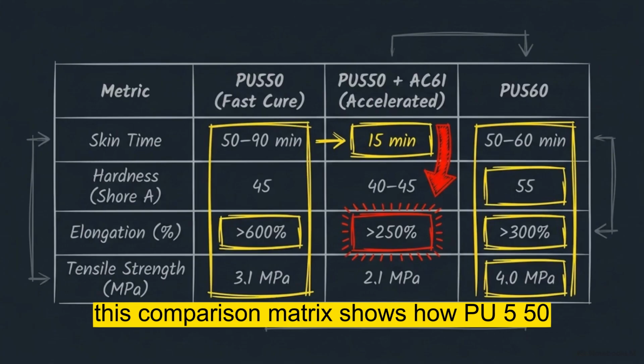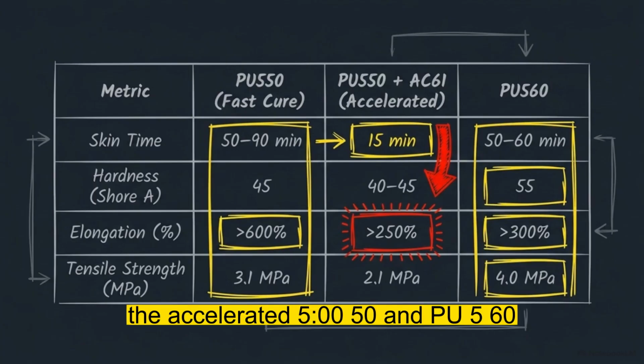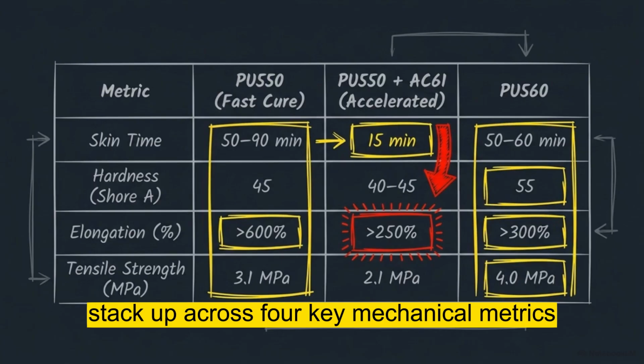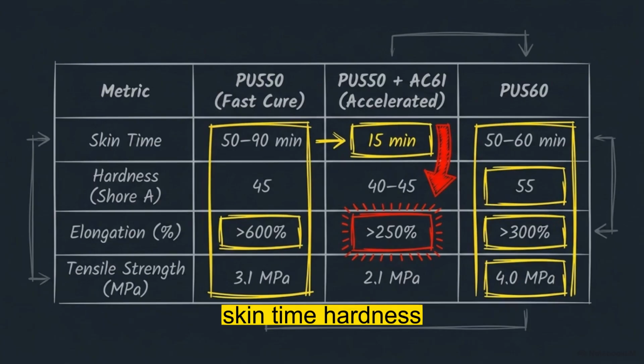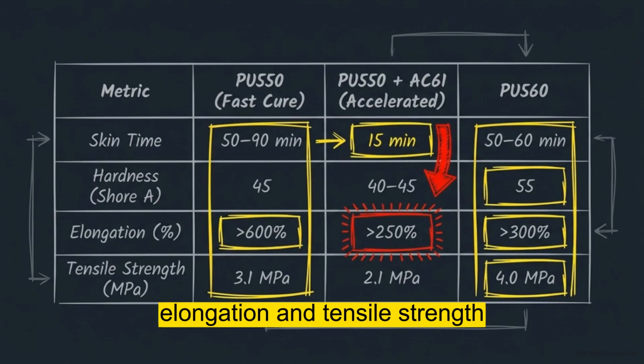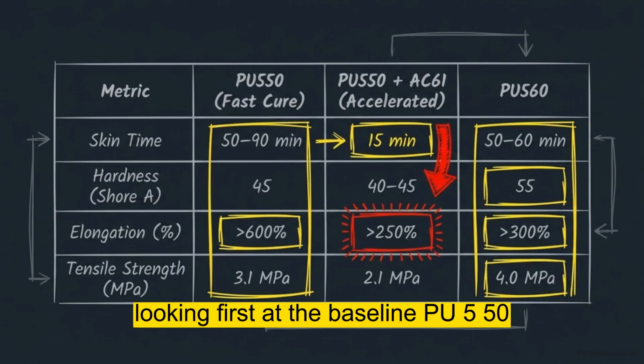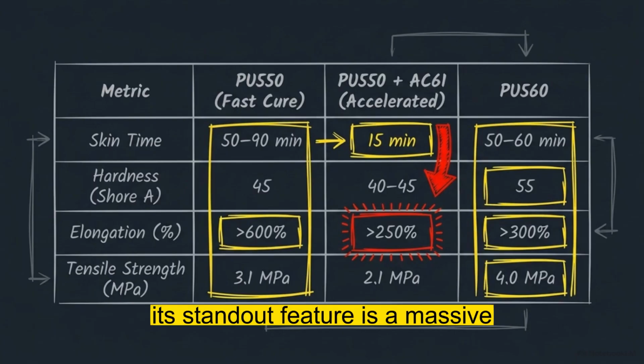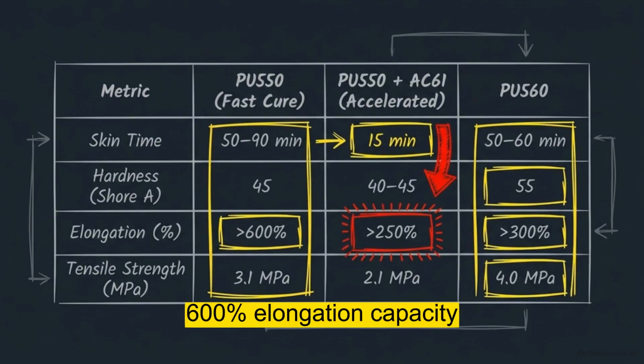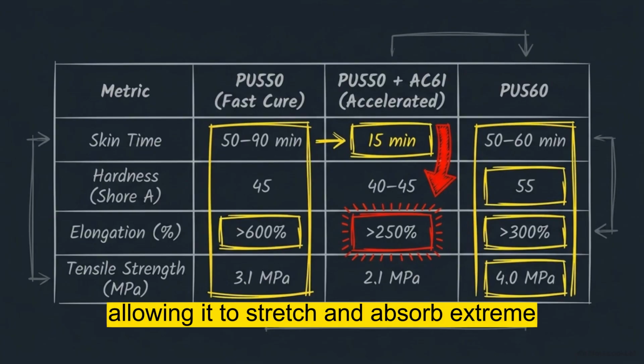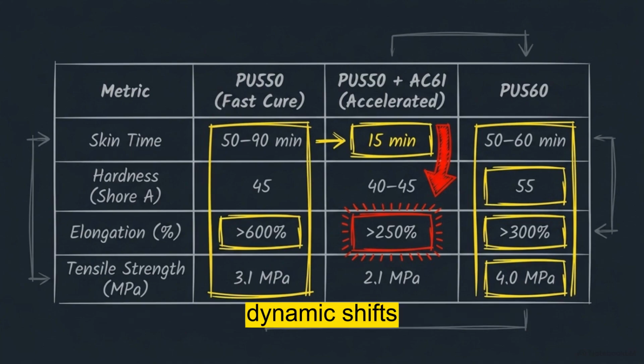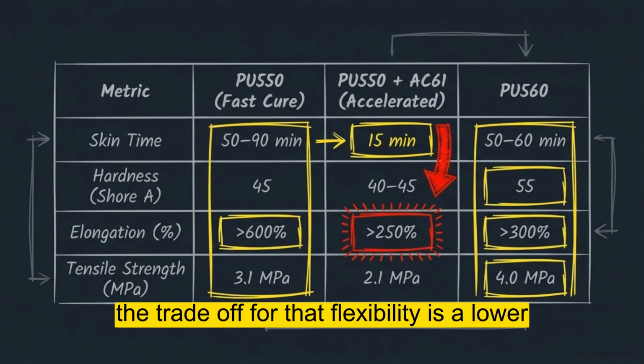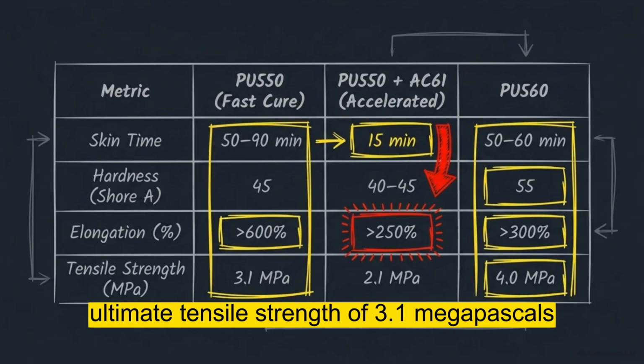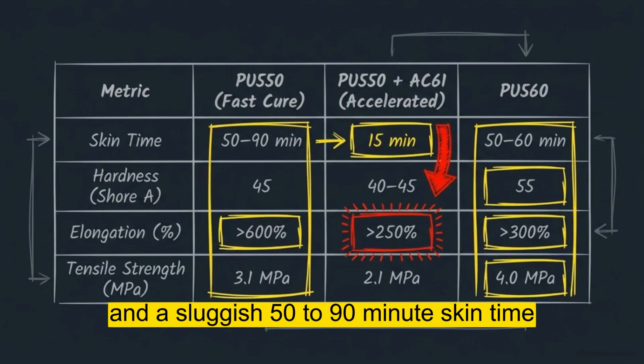This comparison matrix shows how PU550, the accelerated 550, and PU560 stack up across 4 key mechanical metrics: skin time, hardness, elongation, and tensile strength. Looking first at the baseline PU550, its standout feature is a massive 600% elongation capacity, allowing it to stretch and absorb extreme dynamic shifts. The trade-off for that flexibility is a lower ultimate tensile strength of 3.1 megapascals and a sluggish 50 to 90-minute skin time.